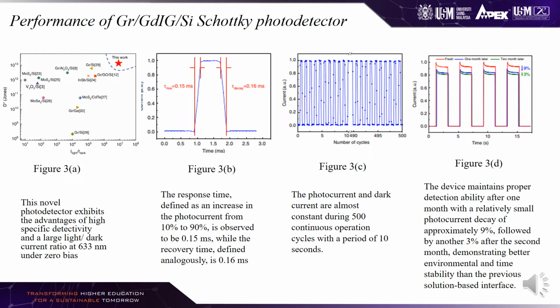Figure 3c shows the photocurrent and dark current are almost constant during 500 continuous operation cycles with a period of 10 seconds. Figure 3d shows that the device maintains proper detection ability after 1 month with a relatively small photocurrent decay of approximately 9%, followed by another 3% after the second month, demonstrating better environmental and time stability than the previous solution-based interface.